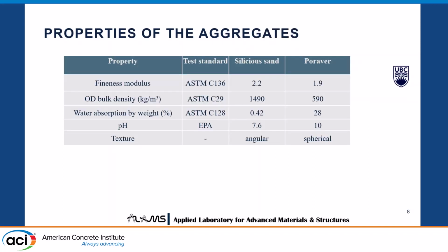And here we can see the properties of the two aggregates that we used. Okay, so if you look at the FM, the silica sand had an FM of 2.2, but the Poraver that we used had an FM of 1.9. And the interesting thing is the oven-dried bulk density. We can see that the silica sand had a density of 1490 kg per meter cube, but the Poraver only had a density of 590 kg per meter cube, which is pretty light.